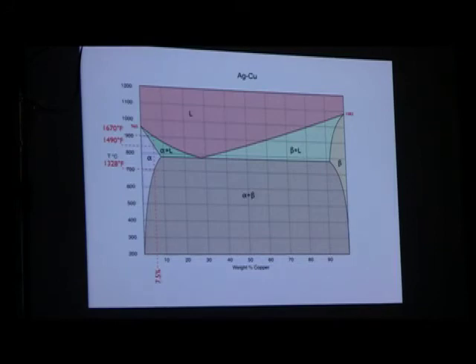And if anybody's heard about age hardening or heat hardening sterling, you have to get it up into that alpha phase to get a full softness. If you heat it up to that temperature and quench it, it'll be almost as soft as fine silver. And then when you quench it, it locks it in that single phase solution. When you bring it back down to, say, room temperature and then come up to 500, 550 degrees for half an hour, you'll precipitate out the beta crystals along the crystal boundaries between the larger alpha crystals, and it basically pins or locks those crystals so that they can't move. That's what makes it really hard.